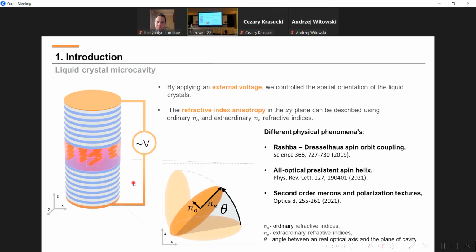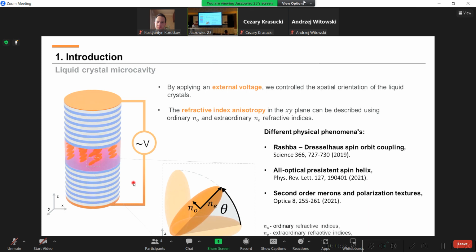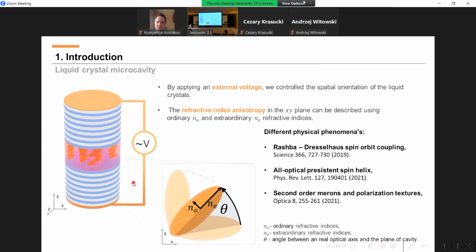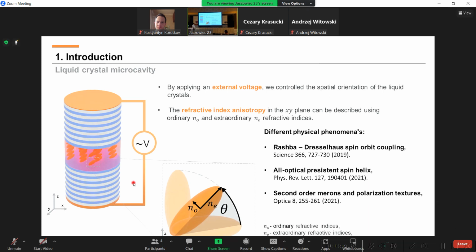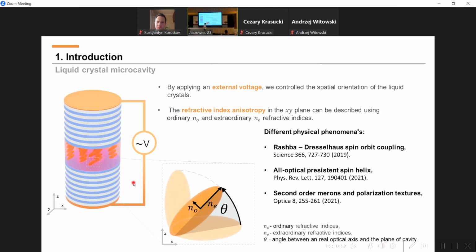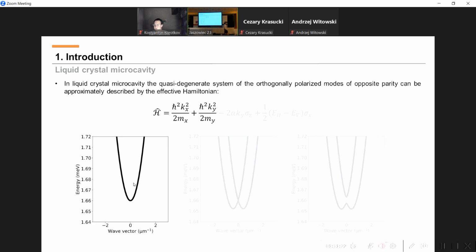And we can control the refractive index of the liquid crystal just by tuning the potential put on the top of the microcavity. And this is very nice because, thanks to that structure, we can change the polarization properties of the photons inside the cavity. During the last years, such a system was widely explored to show different physical phenomena such as Rashba-Dresselhaus spin-orbit coupling, optical persistent spin helix, or creation of second-order merons or different polarization textures.